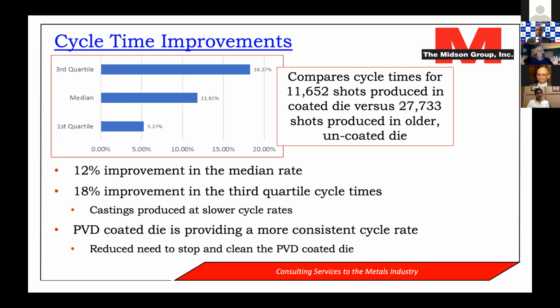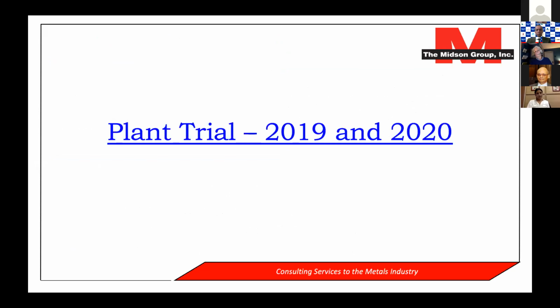And what we think is happening is that the PVD coating is producing a more consistent cycle rate because the caster didn't have to stop and clean the die so often. They didn't have to go in there and clean solder off the die quite as often with the PVD coated die, so they could actually go 18% faster. So a big improvement in cycle rate, which obviously again comes down to cost.